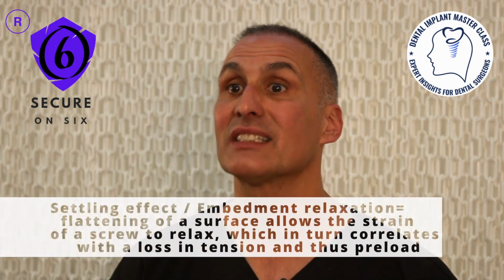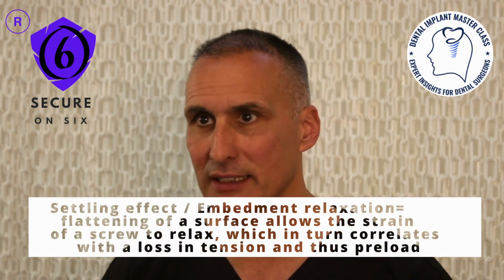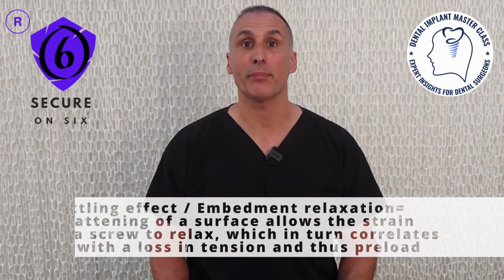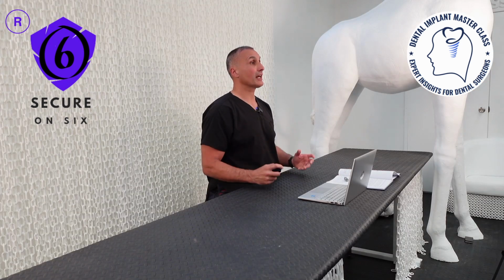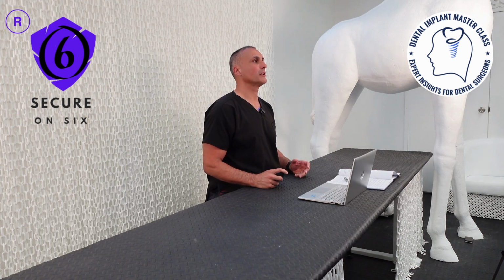These movements can lead to wear of the contact areas, bringing the two surfaces closer together. This phenomenon is referred to as the settling effect or embedment relaxation. The magnitude of settling depends on the initial surface hardness and the extent of the loading forces. Rough surfaces and large external loads increase the settling effect. When the total settling effect exceeds the elastic elongation of the screw, it loses its contact forces and can loosen. And we will discuss the countermeasures to this in more depth a little later.